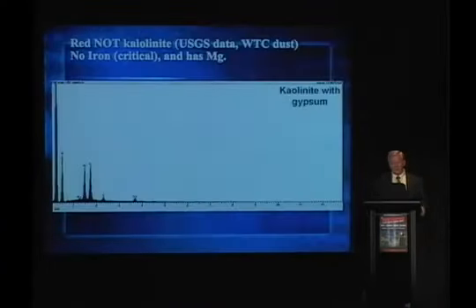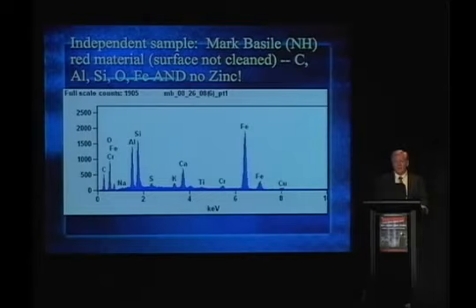They're not the same. We also had a reaction from a debunker who said it's kaolinite. If you'd done a little checking, the USGS data shows this kaolinite. Sure enough, it has aluminum, oxygen, and silicon, but no iron. And so it's just not the same. Furthermore, the behavior, here's an independent sample. The behavior when we ignite this stuff, comparing and when we treat it with a paint solvent, these are entirely different behaviors between the primer paint and the red chips.